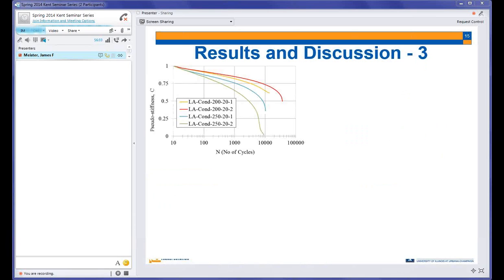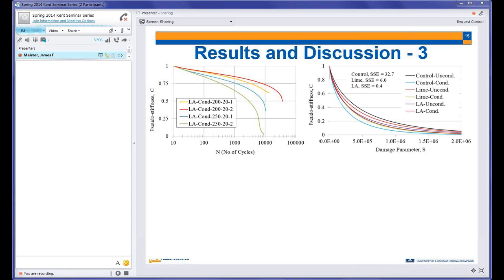The last test is the push-pull test. These are the results that we get from the push-pull test. These are the preliminary results, which are the pseudo-stiffness versus the number of cycles. And this is a sample result for the liquid anti-strip conditioned mix after 5 freeze-thaw cycles. We have 4 samples. We test 2 of them at 200 microstrain, 20 Celsius, and the other 2 at 250 microstrain at 20 Celsius. From this curve, what we really want to look at is the pseudo-stiffness versus the damage parameter.